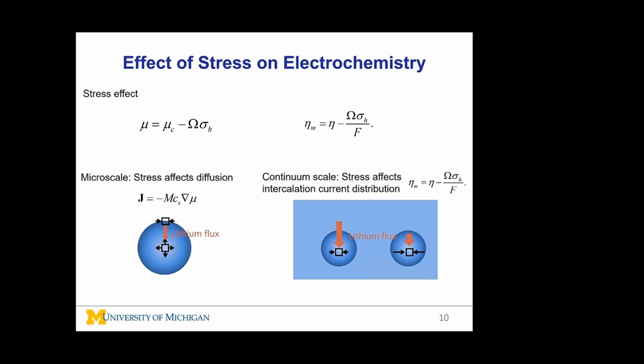In addition, large stress can squeeze lithium ions out of a particle and integrate them into a particle under smaller compression. Therefore, mechanical stress can significantly affect lithium-ion flux at the electrode level.